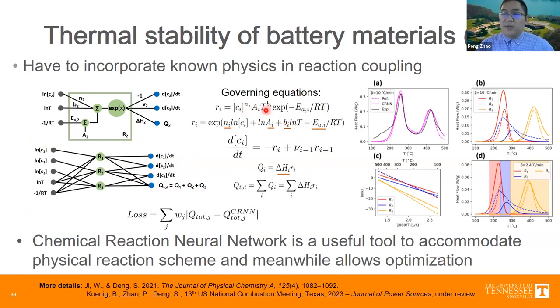Eventually, if you implement this in the chemical reaction neural network, you come up with a well-defined optimization problem. The target is to select a set of kinetic parameters that can minimize the difference between the DSC results and the simulation results. Right? So eventually you can see that by using the CRNN method to study the aforementioned complex phenomena with two peaks merging, we still observe the correct physics where your first reaction is here, the second reaction is here, third reaction is here, they are decoupled, instead of the dashed line where the second reaction occurs in front of the first reaction. And that also agrees with the temperature range as indicated by the in situ XRD.